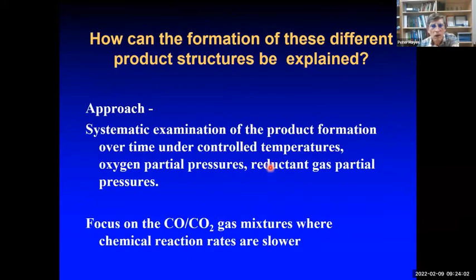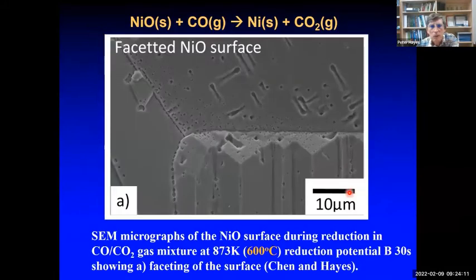Okay, so let's have a look at some of these microstructures that are formed on the surface of the sample. We're going to start at 600 degrees centigrade, and we're going to examine the surface using a scanning electron microscope. So this enables us to look at very low,